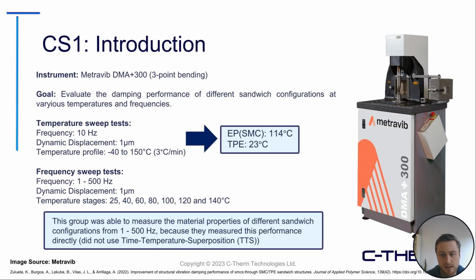The DMA test they did with these sandwich structures was with a Metravib DMA Plus 300 with 3-point bending, and the goal was to evaluate the damping performance of these different configurations at various temperatures and frequencies.